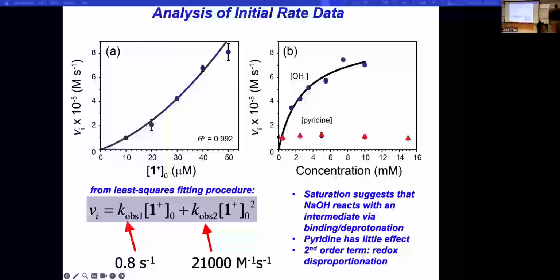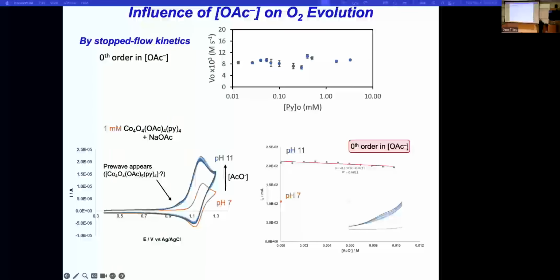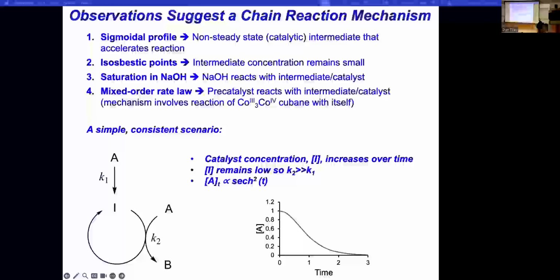The reaction shows saturation behavior in hydroxide, and there's no concentration dependence with the pyridine. So the pyridine isn't coming off to open up a coordination site, but hydroxide is attacking. We get this saturation behavior, and the hydroxide concentration is buried in this apparent rate constant here. So pyridine has little effect, and what we've also found since we published the first paper on this is that acetate concentration doesn't either. So acetate isn't dissociating to open up coordination sites either. We think it swings away to go kappa one to open up a site, but it does not fully come off.